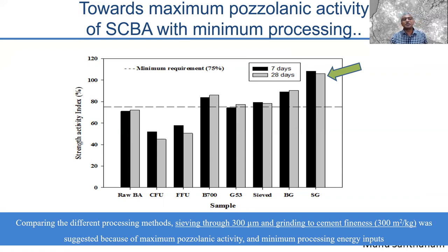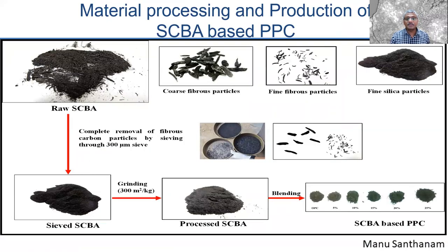What you simply do is crush it to a size equivalent to that of cement. About 300 square meters per kilogram is typically the fineness that we used in our research studies. And we found that that material in combination with cement produced nearly 100% effect. So that's what we went with as far as using blended cements with SCBA are concerned.